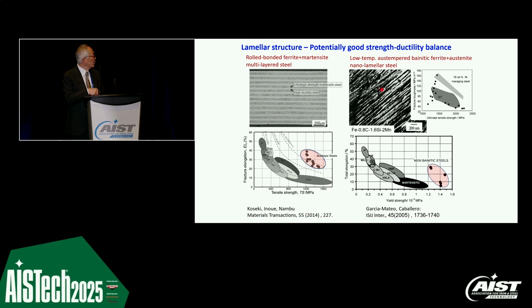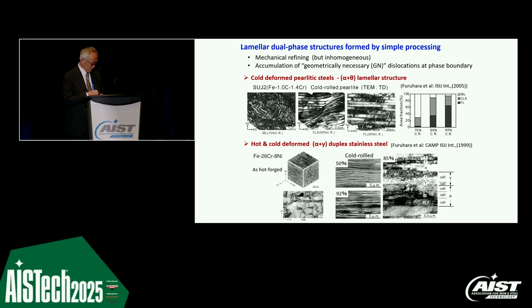And this is, of course, the famous nano-bainite, a lamellar austenite and bainite structure, produced by Professor Harry Bhadeshia and also Professor Francisca Caballero, and they obtained very high strength and very nice ductility. So those two are typical nano-lamellar structures for very high strength and very high ductility. Of course, we know cold deformed pearlite can produce such microstructure.